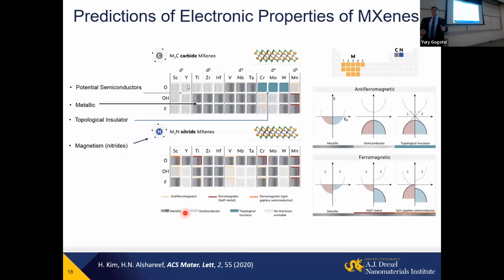There are also many other interesting properties predicted, which again, I'm not going to discuss today. Some of them have been demonstrated, some of them not. By pulling electron density away from the transition metal by, say, oxygen termination or chalcogen, you can open a band gap, making semiconducting MXenes. Topological insulators have been predicted, many of them in this family. Two-dimensional ferromagnetic and antiferromagnetic materials again have been predicted. Superconductors have been predicted actually 2 years ago. Dmitry Talapin's group from the University of Chicago demonstrated semiconducting sulfur and selenium terminated MXenes. Many others, like topological insulators and 2D ferromagnets, are still to be experimentally demonstrated. So again, plenty of room to discover.